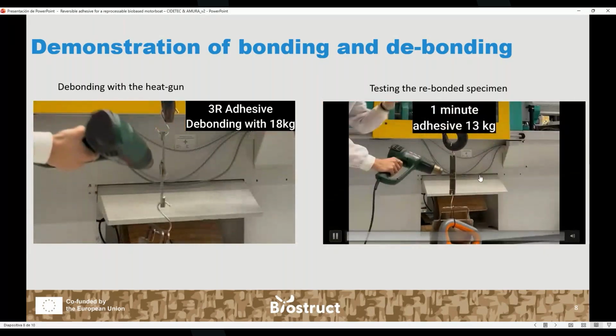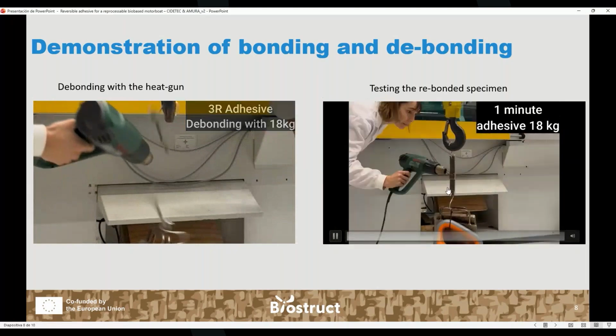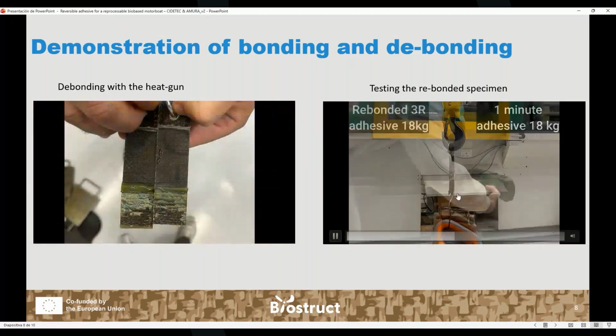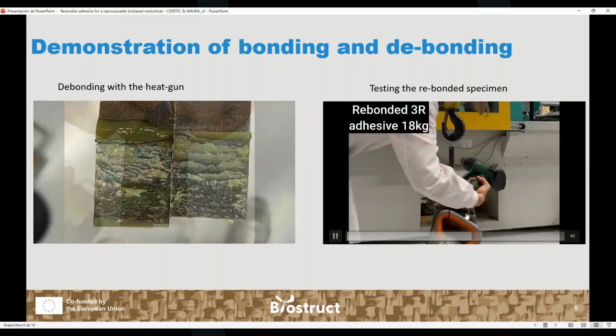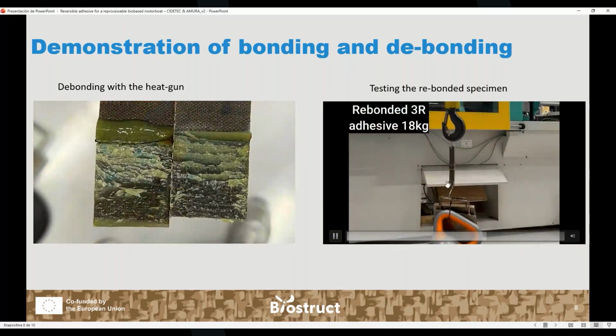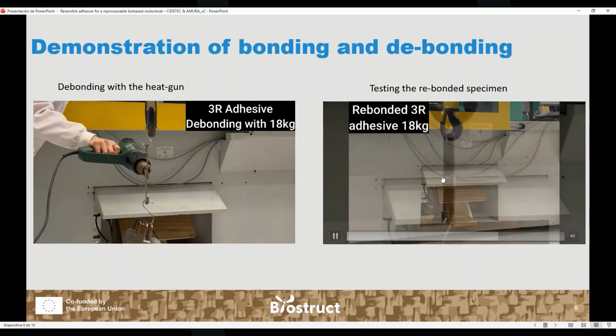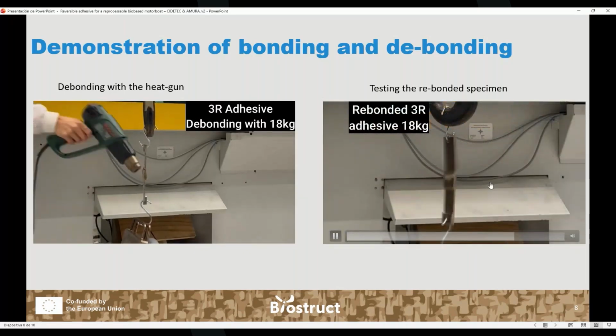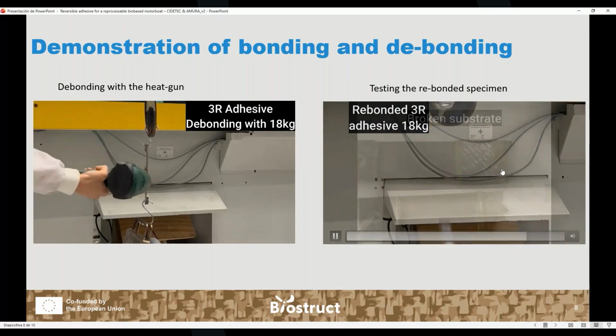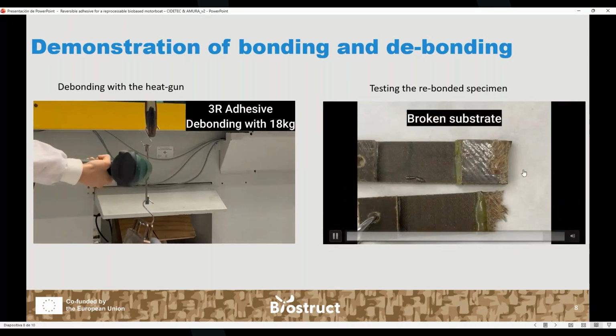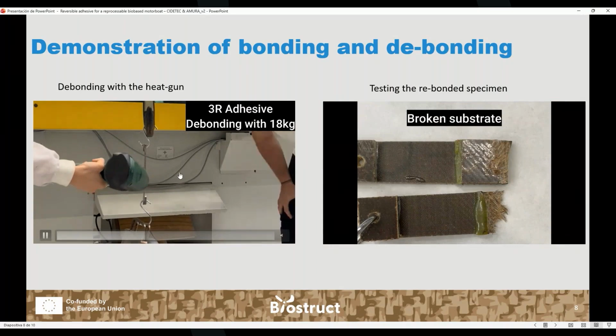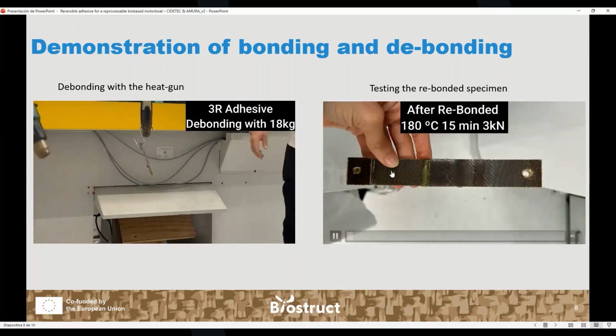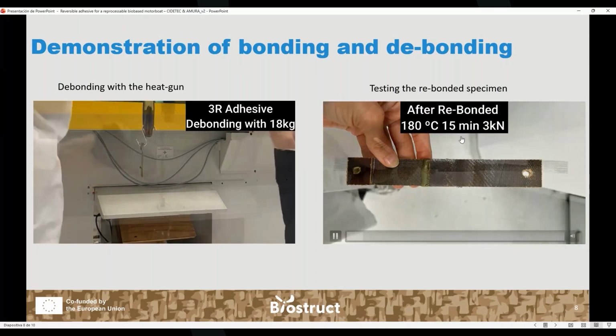and we tested again the rebonded specimen, and you can see that it's repaired, and we obtain a breakage of the substrate, not of the bond. So we can say that the developed adhesive is debondable and also rebondable on demand.